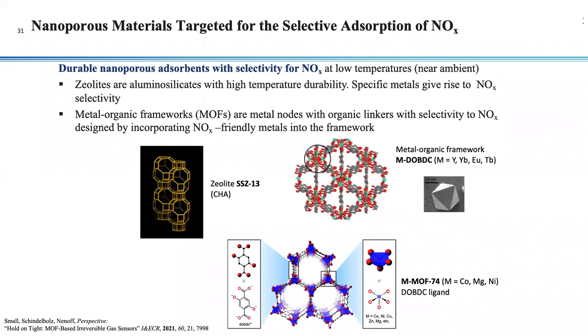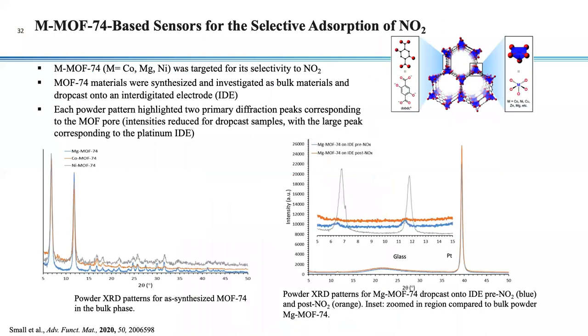We are using platinum interdigitated electrodes on a glass substrate. We use our MOFs — because they are so adsorbent to their target gas molecules — so we don't have to worry about other gases interfering. We'll talk about nickel MOF-74, a nickel-based metal organic framework using DOBDC. We expose it to gases — in this case 5 ppm NO₂ for eight hours at 50°C — and get a direct electrical readout with very low power consumption. X-ray patterns confirm we have the MOF on the interdigitated electrode, and the same framework pattern regardless of which metal is used.